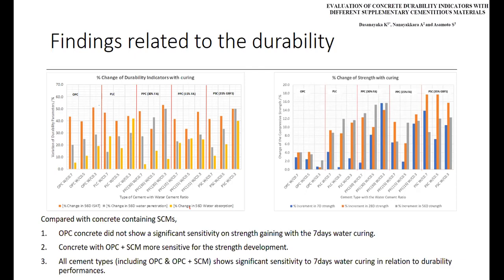We have initially prepared a concrete sample and it was placed inside pure water for 7 days for the requirement of water curing. And the same kind of sample was kept at ambient condition without doing any kind of water curing. Then we have tested both samples following these test methods. And then we have recorded what is the value given for the ambient cured sample and what was the value delivered for the water cured sample. Then we have developed what was the difference or improvements of the durability between the ambient cured sample and the water cured sample.